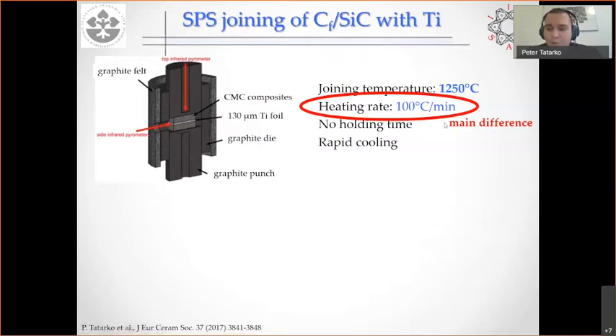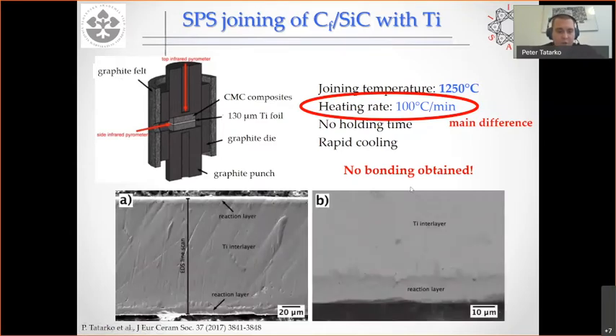If you remember, for flash SPS, it was 9,000 degrees C a minute. So significant difference. At the end, when we apply this kind of process, we didn't obtain any joint. So you see this is just the cross section of the delaminated form. So basically what happened, we tried to join, and then after joining, the CMCs fell apart, and we only got this delaminated titanium form.